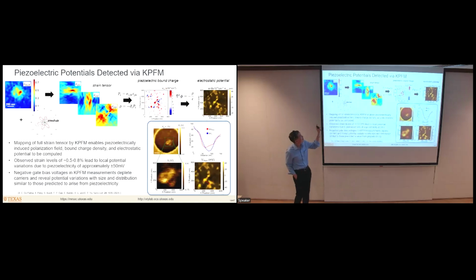If we come back then to the TMDs, the path that we're following is that we've used this Kelvin probe microscopy technique to determine the hydrostatic strain distribution. From that, we can get the full strain tensor. We combine that with second harmonic generation to get the orientation of the crystal relative to these axes. And then we can calculate the piezoelectric polarization and the corresponding bound charge. We get this over here, right?